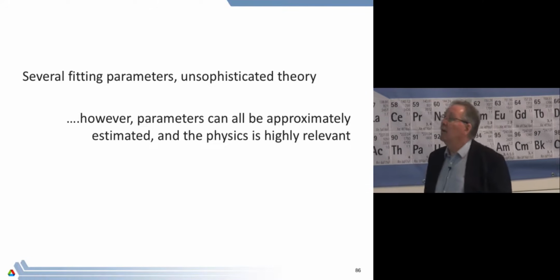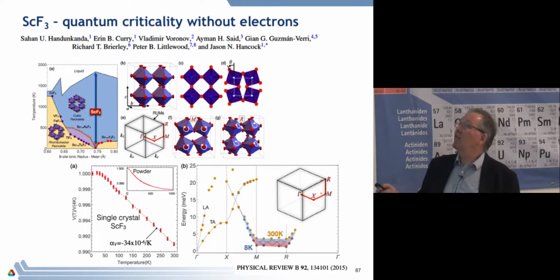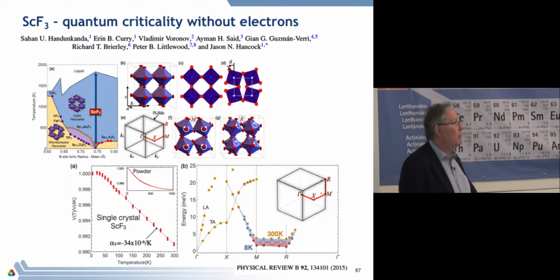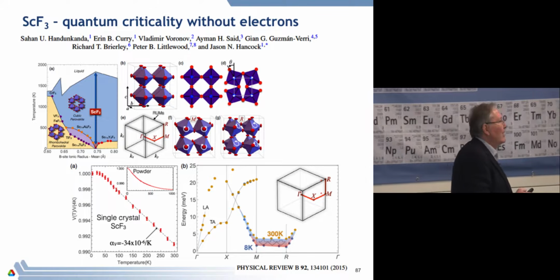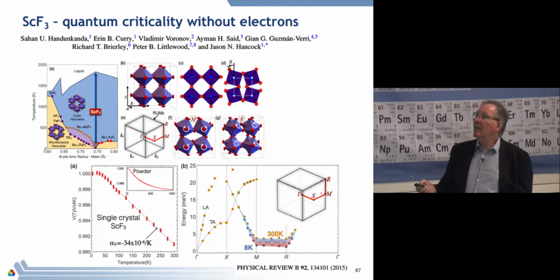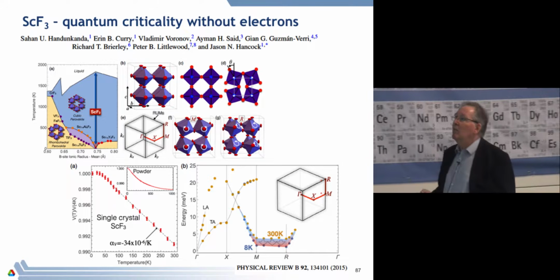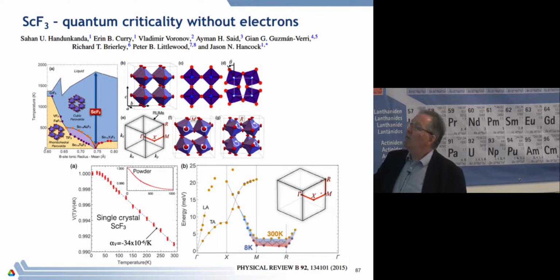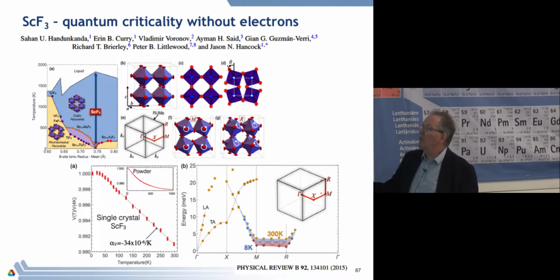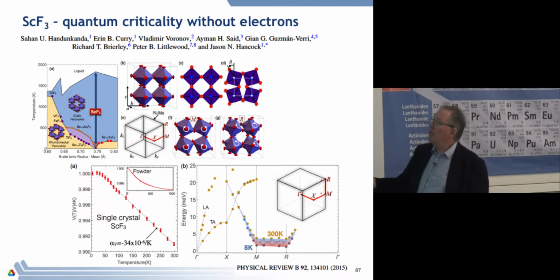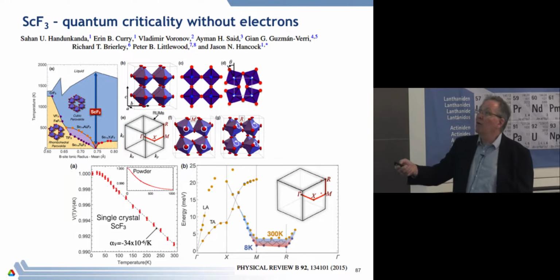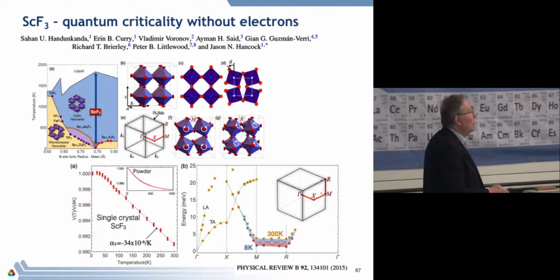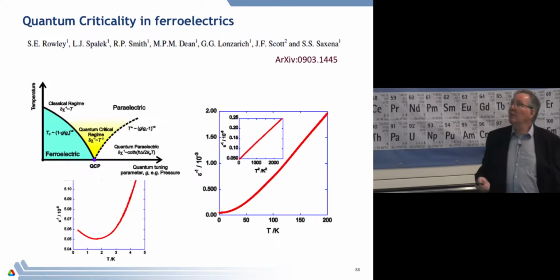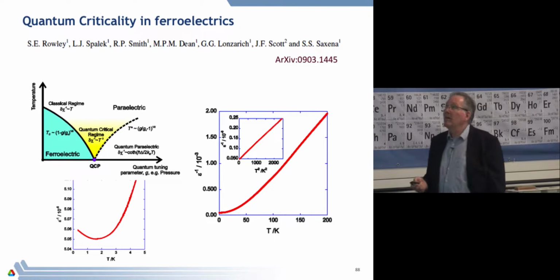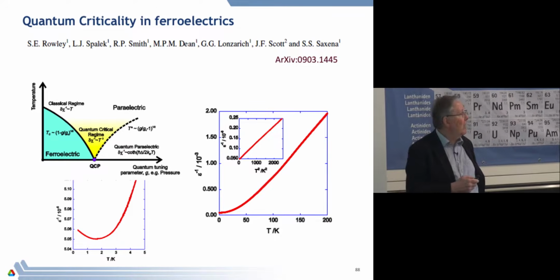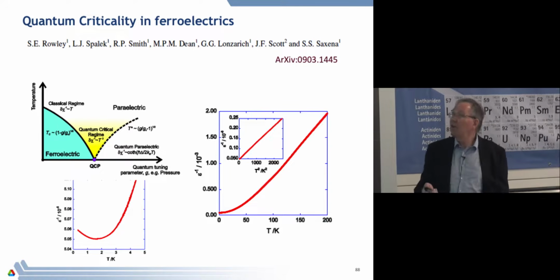There's even some nice materials to look at. My favorite, actually, at the moment is scandium trifluoride. This is a material which is really officially a negative thermal expansion material. It's a very large gap insulator, but interestingly, it has very soft rotations associated with all of these things, and those rotations seem actually to be diverging very close to T equals 0. This seems to be an elastic quantum critical point. Similarly, strontium titanate is famous for being an elastic quantum critical point.